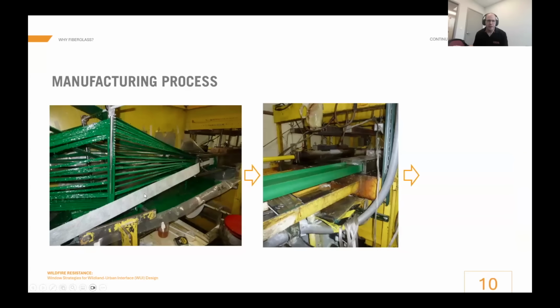When fiberglass is manufactured, long strands of glass fibers get oriented into the necessary shape for the tooling to produce the end profile. Then those fibers get coated with resin, and the resin is not always green as it shows in this photograph, but you can make it that way if you want. The material gets pulled through a die that heats the material and gives it its shape. And finally, you have an unlimited length, two-dimensional profile that you can cut and then manufacture into anything you want.